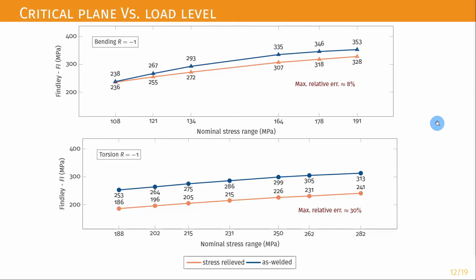So, what is presented here is the first numerical investigation where we tried to provide an answer to the different behavior between torsion and bending. First of all, damage was studied in the most critical point of the weld bead, in our case the weld root. The damage was calculated using critical plane factors.